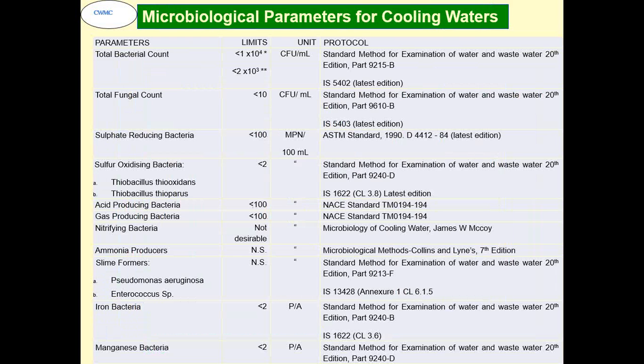These are typical microbiological limits. TBC, or total bacterial count, should be less than 10^4 CFU per ml, preferably less than 2 into 10^3. TFC less than 10 CFU per ml, SRB less than 100 per 100 ml, sulfur oxidizing less than 2, acid producing less than 100 per 100 ml, that means less than 1 per ml, gas producing bacteria less than 1 per ml, nitrifying bacteria not desirable, ammonia producer not specified but not desirable, slime formers again not specified but not desirable, iron bacteria less than 2, manganese bacteria less than 2. I have given the protocol also by which they are tested.